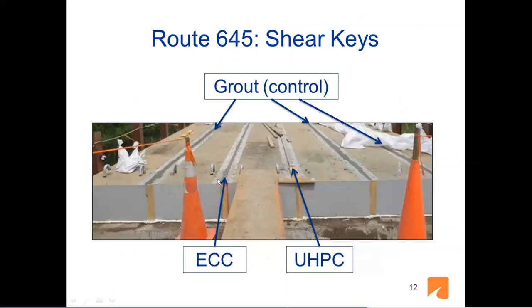And then we also placed ECC, as you see here. And then we also placed UHPC. This UHPC mix was not setting on time. It took us almost a day for it to set, and it was flowing. As you look carefully, you will see that we put wooden planks to keep it in place, because these bridges have a grade to them, I think maybe about 3% grade, and the UHPC was not setting on time and was flowing down. I understand that now they have other versions of UHPC, and some of them set within hours, and I hope that they won't have this problem anymore.